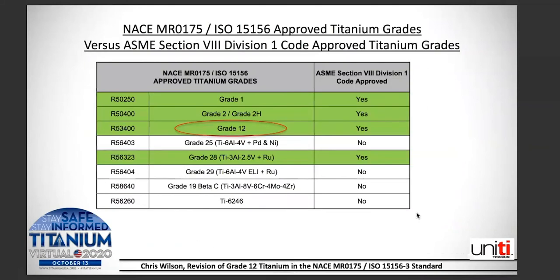Now, looking at which grades are approved within the NACE standard, and then also approved within ASME Section 8 Division 1 code, you can see that 4 out of the 8 grades are approved titanium grades within the ASME Section 8 code. Those being grade 1, grade 2/2H, grade 12, and grade 28 with the Ti-3Al-2.5V with ruthenium.